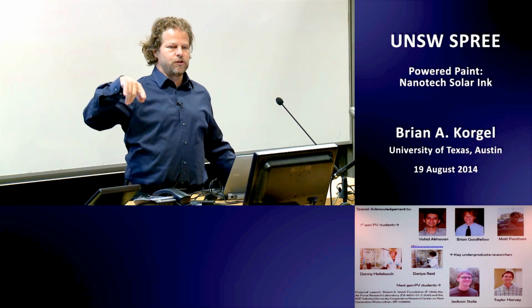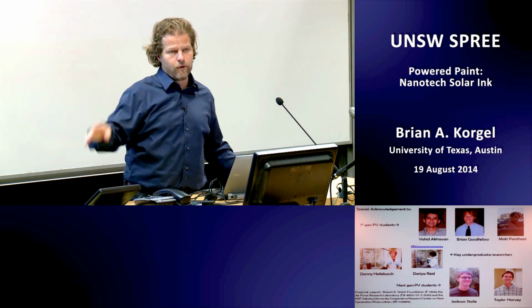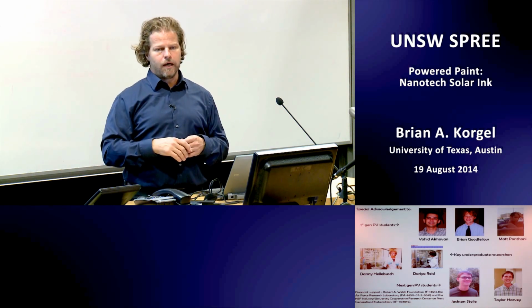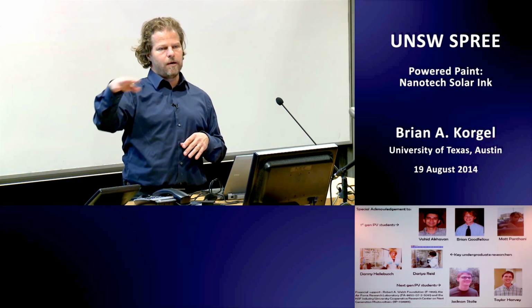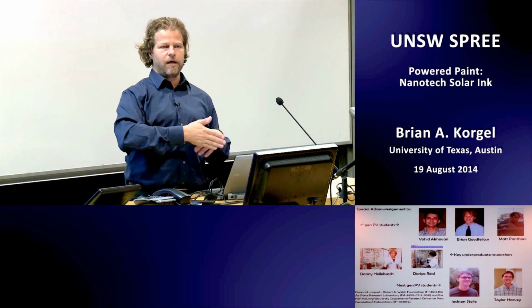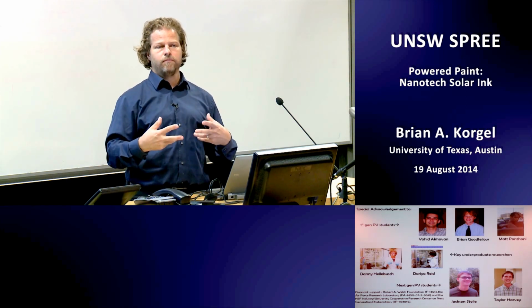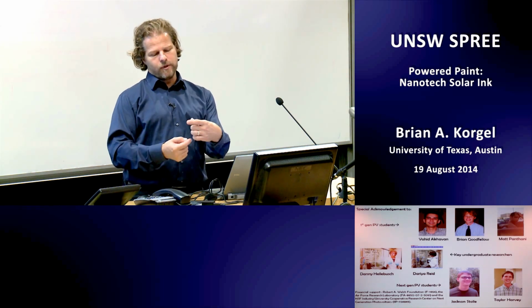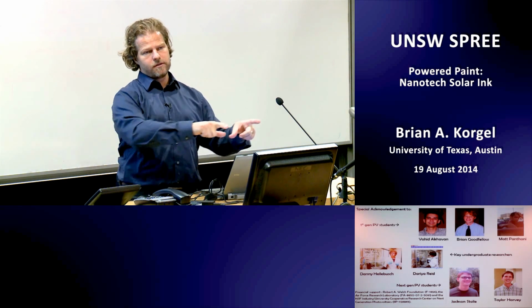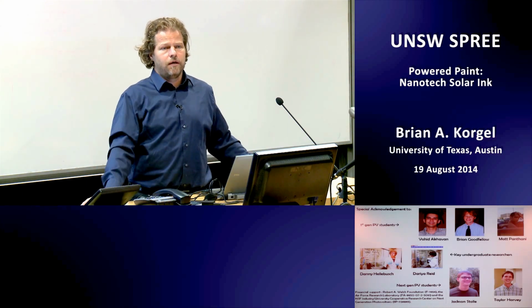Yeah, I should have mentioned that. The first TAS measurements I showed were on the film, so that's what we looked at initially, and then the 3 different sizes were actually dispersions of nanocrystals. So where we got the MEG threshold, those were dispersions of nanocrystals. So we've done both. One of the things we checked in the thin films, I don't know how many of you look at carrier multiplication, but you can have charging that can influence your measurements. Some of the early papers on carrier multiplication had really high MEG efficiencies, and the reason was that they weren't accounting for photocharging. So when you do these measurements, you have to stir the dispersions to eliminate that, and in the thin films we were translating the stage, making sure that there wasn't a problem with photocharging. So we've looked at both films and dispersions.